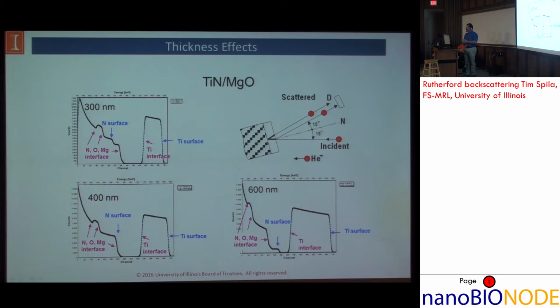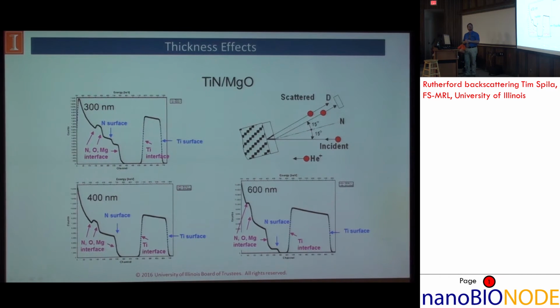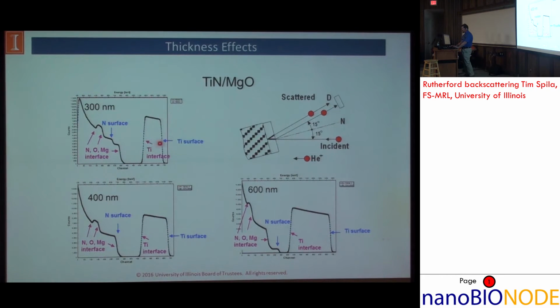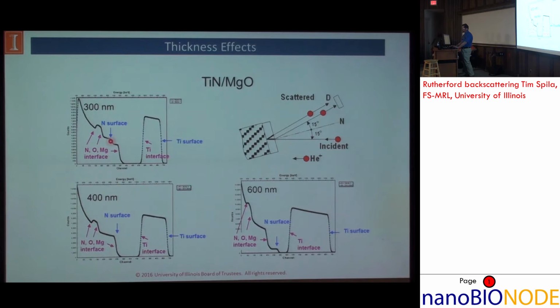We do have thickness effects that can occur in RBS, so it's something to be wary of. So we have a titanium nitride on MgO film here. And so you can see we have the titanium signal here. So here's titanium at the surface, here's titanium at the interface, here's nitrogen at the surface, and our substrate is MgO, so this is a buried layer.